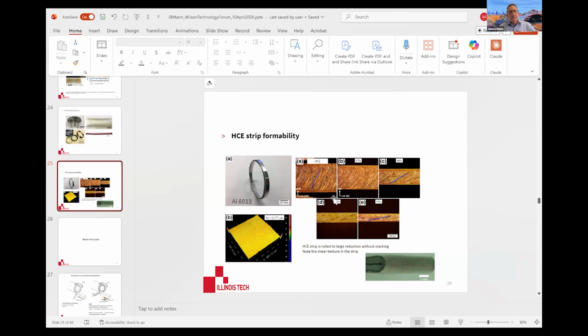But the thing that's maybe more important to take away here is, and I don't have a picture of normal rolling here to show you, that the normal texture orientation in rolling is in the direction of rolling. And that's the only direction you can achieve in rolling. But in this metal cutting configuration, using hybrid cutting extrusion, we can actually influence the orientation of the microstructure, the orientation of the shear. So we get these different shear flows.